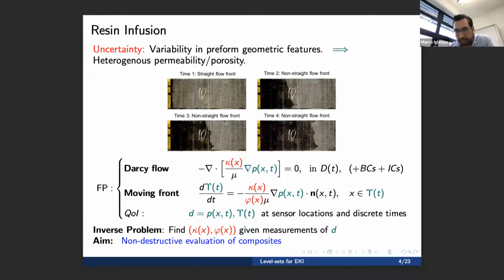characterize this variability, because that is critical not only in the injection of the resin, but in some cases this variability can compromise the performance of the material when it deviates from the nominal or the design value. So what you can see here in this cartoon is the resin. This dark area is the area that has been filled with resin, and it's not a straight front when it's supposed to be a straight front.